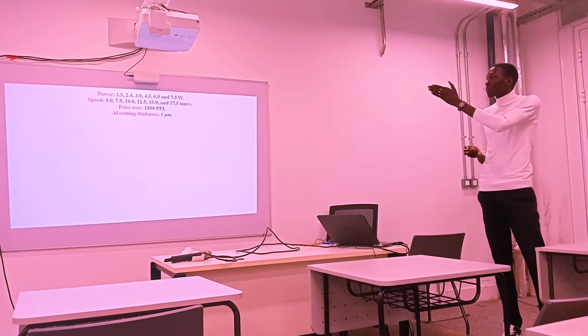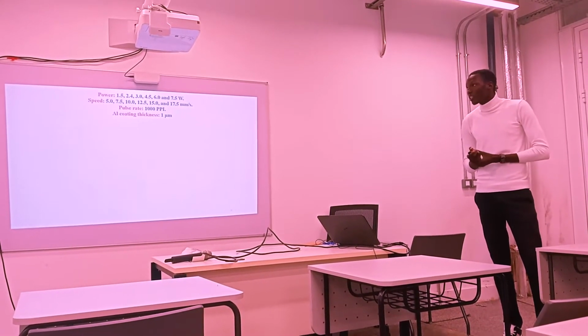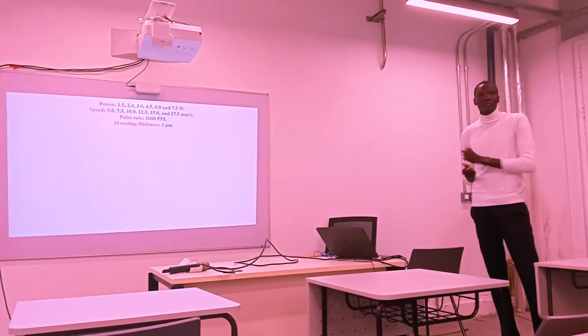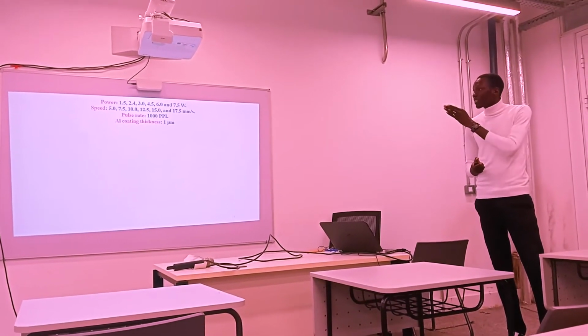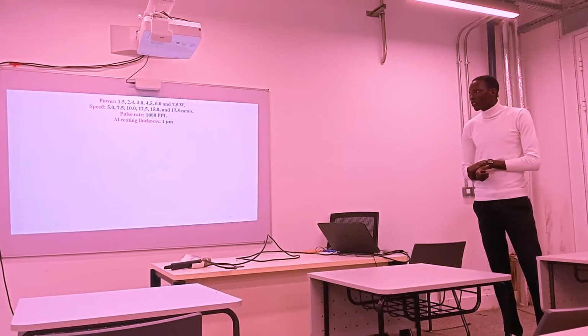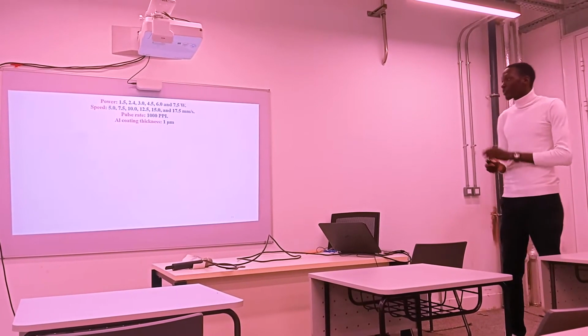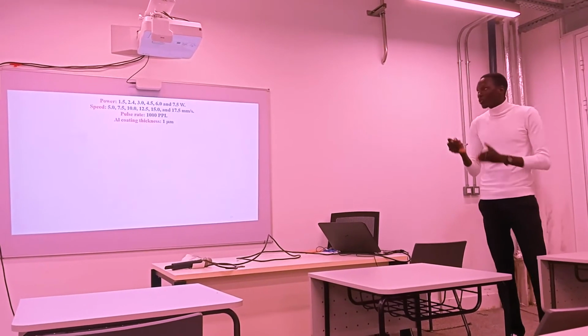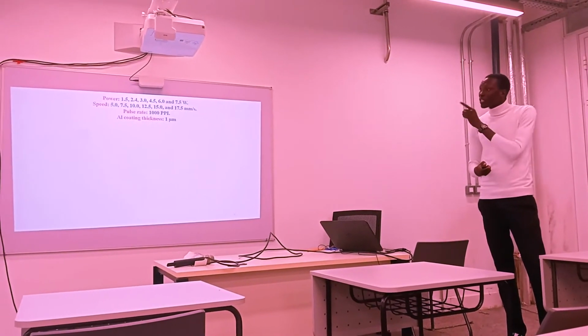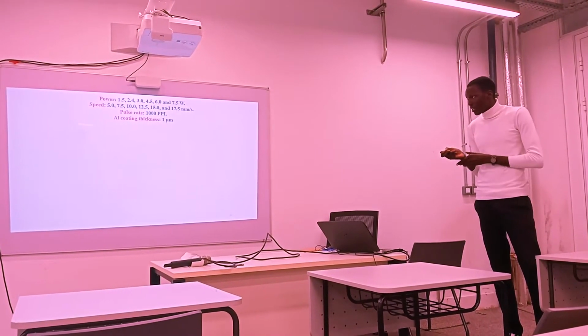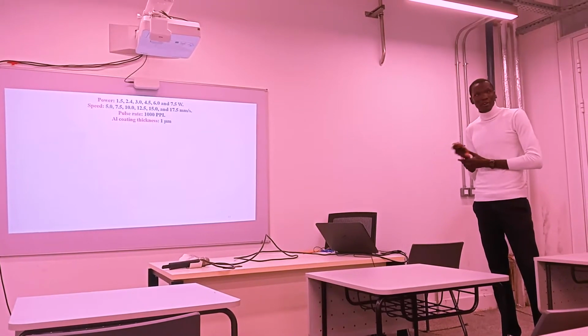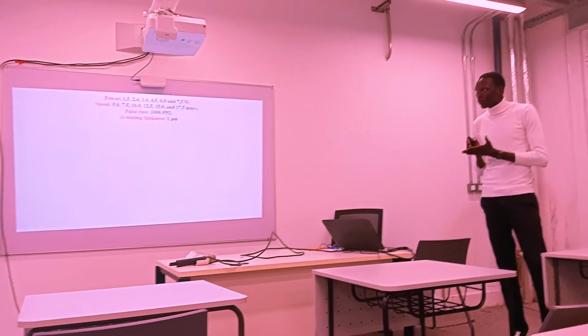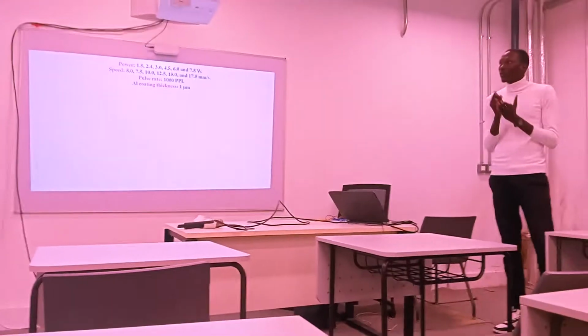We used power from 1.5 to 7.5 watts, speed from 5 to 17.5 millimeters per second, and we fixed the pulse rate at 1000. You may wonder why. Because the maximum value gives the best results. So we fixed it. And we coated with a one micrometer layer of aluminum before fabricating the channels. We fabricated in air and with the aluminum, and then we compared the results. And we found very interesting results.